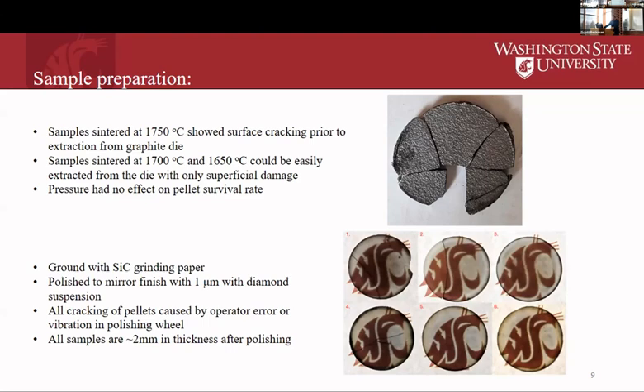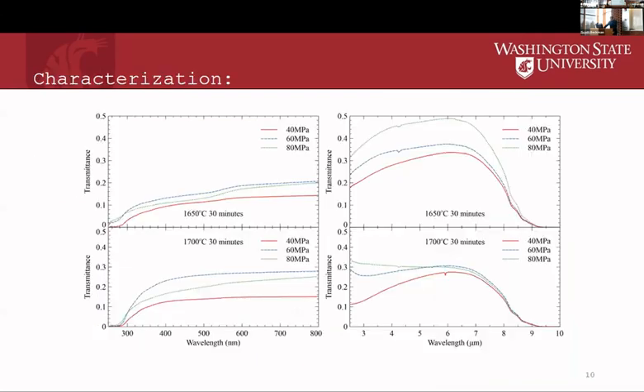Approximately 1 micron diamond polish was used. As you can see in a few of these, I think 3 of them, you can see cracks in the pellets. It's important to note that those cracks were all developed during the polishing process, either by user error and catching the edge of a pellet on the polishing cloth and cracking it off, or we had problems with excess heat during polishing, where rapid heating from friction between the pellet and the polishing medium ended up cracking a few of the pellets.